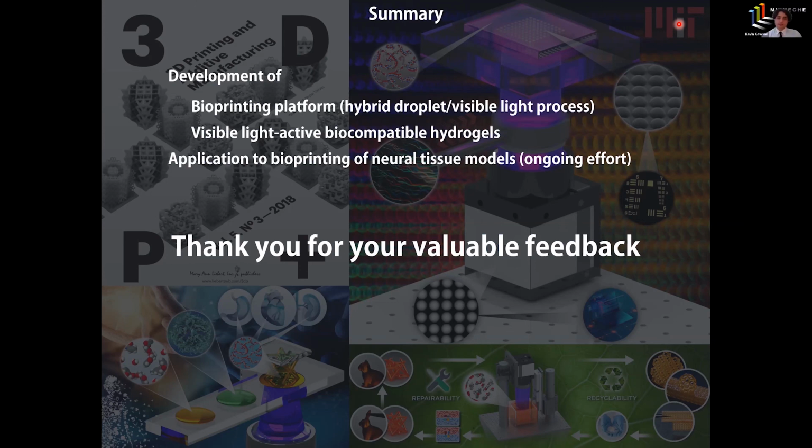Yeah, I would say the material science part of this research is quite heavy, and these materials are not only expensive, but there are many different variables in terms of the ECM, the extracellular matrix materials. And so, for example, here we're using visible light, which is somewhat new for bioprinting. And so these materials have to be tailored towards being active or responsive to visible light. So there are a wide range of different photoinitiators, or visible light photoinitiators, that need to be tested in terms of their biocompatibility, in terms of the speed of the process or the cross-linking. So I would probably spend most of the money on material development and testing, because it's all about the environment that we create for these cells. And if we could create a nice one, then the cells will behave nicely and basically do the job for us.